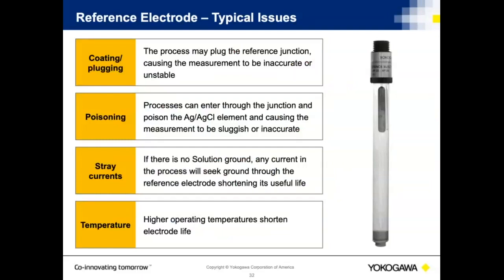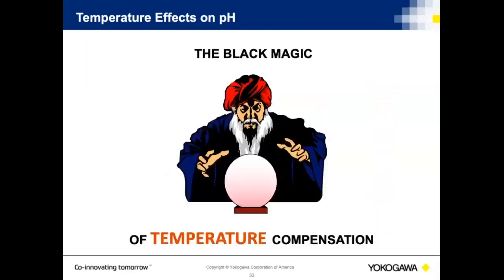Poisoning: any ions in solution that don't like silver chloride will eventually make their way into the reference electrode and poison the actual silver chloride. Stray current: if there's no ground solution in the measuring circuit, any currents in solution will find their way into the reference electrode through that junction. Temperature: just like the measuring electrode, temperature will affect the life of the pH electrode.